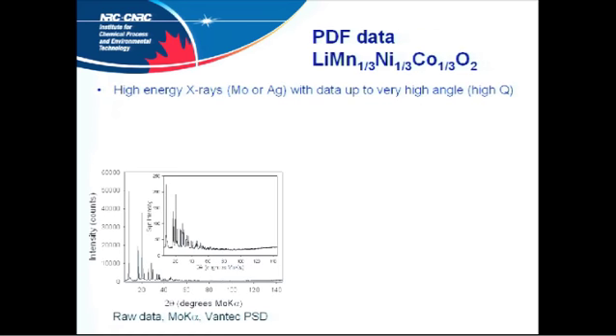Now, 145 degrees here with moly, you're getting to fairly low d spacings, reasonably high Q. I can't remember what the limit from that is. It's about 17 inverse angstrom, something along those lines. And you can get the data. It's actually worth using a PSD because PDF usually wants particularly low noise, otherwise you get artifact problems.